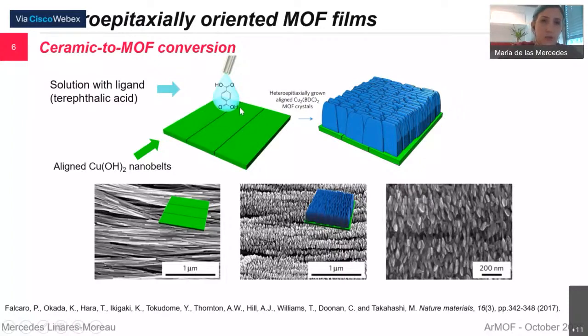So from these substrates that are composed of aligned copper hydroxide nanobelts, which are anisotropic nanostructures around 200 nanometers long, after exposure of the ceramic to a solution containing the ligand, in this case terephthalic acid, this can be converted, using the copper hydroxide substrate as a sacrificial template, to an oriented polycrystalline film, where the crystallites grow heteroepitaxially on the copper hydroxide.